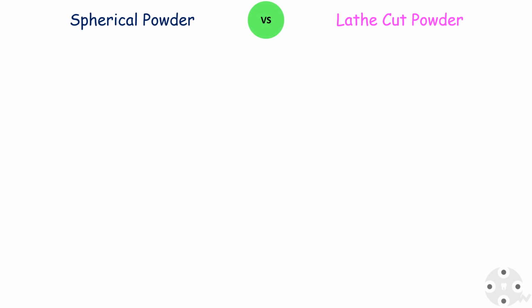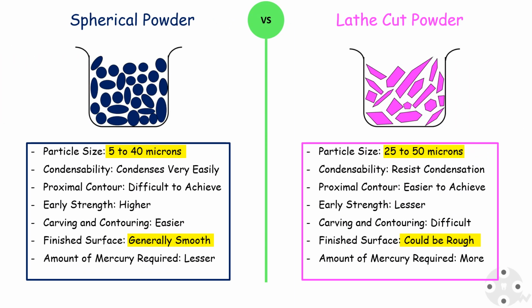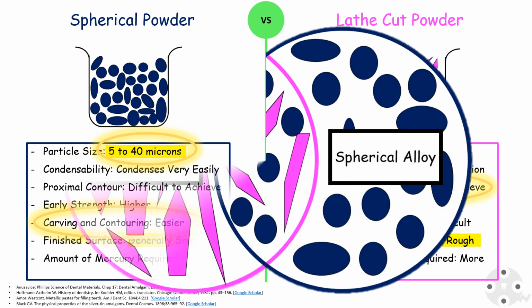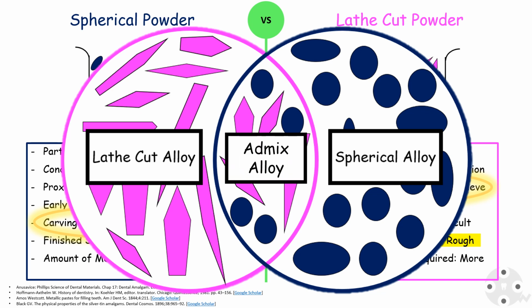Both the lathe-cut powder and the atomized spherical powder have their merits and demerits. The smaller particle size of the spherical powder may make it easier to pack into small areas and allow for easier carving and polishing. But the lathe-cut powder possesses body and gives the amalgam restoration good fracture resistance in areas such as proximal restorations. To combine the best of both worlds, admix alloy powders were introduced, which contained 2 parts by weight of the lathe-cut powder and 1 part by weight of the spherical powder.